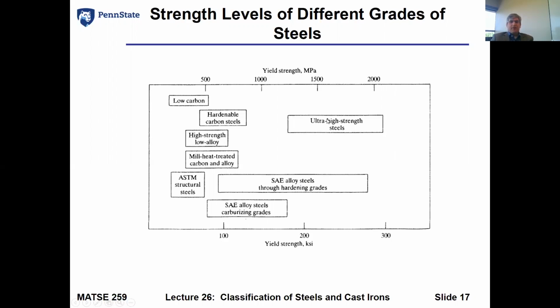And then there's this whole other grade of steels, these ultra high strength steels. Things like the tail hook on Navy fighter jets. That tail hook material is made from an ultra high strength steel. It's a specialized steel. In a lot of cases, Carpenter Technologies in Reading is really well known for their ability to develop and produce ultra high strength steels. And so we started looking at this from a strong steel that we might use for the hull of a ship up to something for a tail hook. There's a factor of 3 difference in yield strength. So you can talk about 300 KSI yield strength. That is an exceptionally strong material at the end of the day.